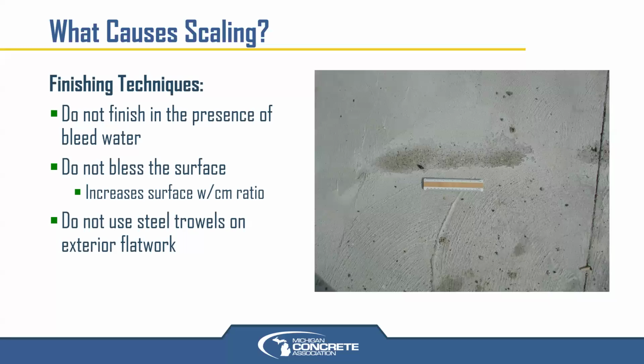But that's what scaling is. What is scaling affected by? Finishing practices? Yes, they will affect scaling. Finishing in the presence of bleed water. As the bleed water is coming up, or prior to the bleed water coming up, you could seal the surface prior to the bleed water coming, and that can cause delamination. Not as prevalent in air-entrained exterior concrete, but could happen. As it's coming up, that could happen too. You're elevating the water cement ratio as the water's coming up from the bottom, bleeding up through the slab, as everything else is settling out. Or you're applying water to the surface during finishing, increasing the water cement ratio, decreasing the strength of the paste, increasing its porosity, making it more of a sponge. Therefore, in the winter, it will then soak up that water and fail.